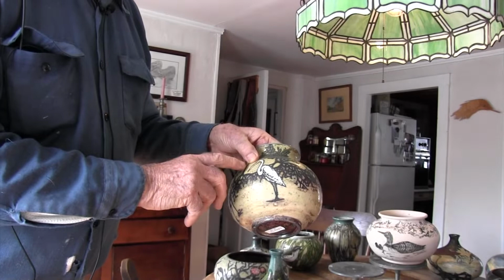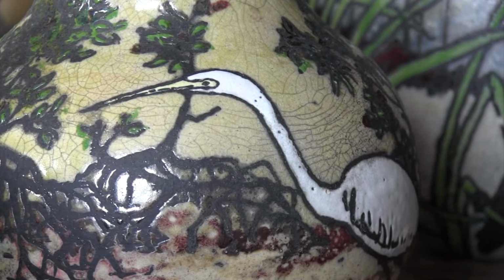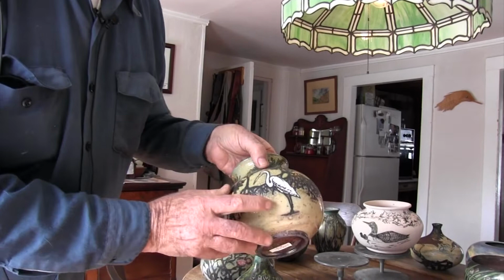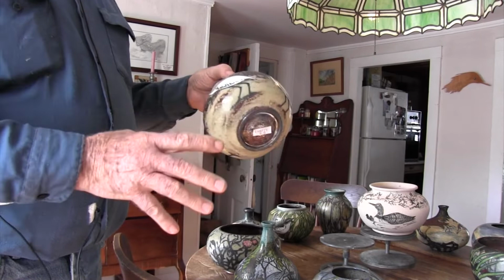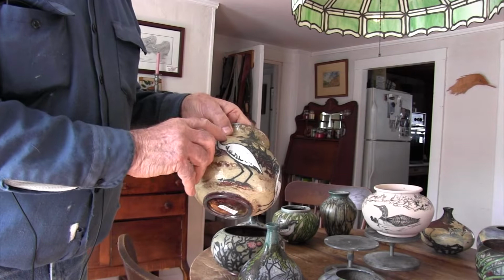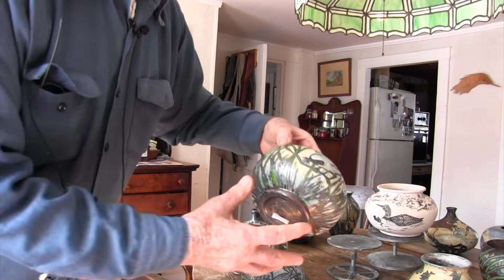These cracked areas, the glass cracks. How you kind of bring this on in a way, you can reinforce that. You never know when it's going to happen. I love it when it does. Sometimes you get very horizontal cracks, and sometimes you get the little checkered cracks. They happen when you yank it out of the combustion chamber and you put it into water. Oh, and this thing will hiss and howl, and that's the fun of it. And it cracks the glass, and then the blackness of the soot and all will go into the cracks, and this is what you'll see there. Sometimes you never know. Sometimes it happens a lot. Unlike this one, it didn't happen at all.